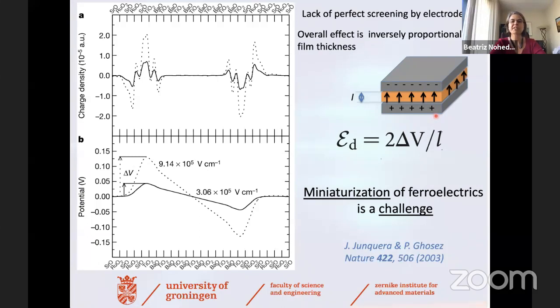So there is always a depolarization field, and as you can see here, this is a ferroelectric layer in between two electrodes, and on top you see the charge density, and you can see it is not fully screened at the interfaces with the electrodes, which gives rise to a potential at the interface that at the end will give rise to a field, the depolarization field, that depends inversely on the thickness of the film. That's why very thin films, when you try to make ferroelectrics really small, will have a very large depolarization field that will kill the polarization. So in short, miniaturization of ferroelectrics is an intrinsic challenge, or we thought it was an intrinsic challenge. And that's why the application of ferroelectric memories was kind of stuck.